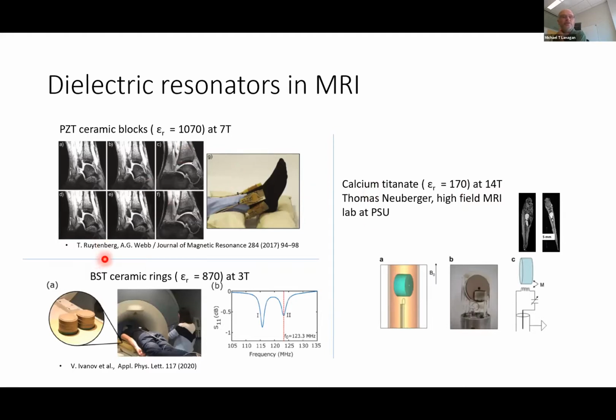Just some examples from literature where we have a dielectric resonator antenna on an ankle shown here, giving a very nice image. This one is one that was done, I believe, in St. Petersburg, where very recently they did some breast imaging using dielectric blocks and then found an enhancement in the signal to noise ratio. And then here, just kind of reiterating what we did on the zebrafish. So these are all dielectric resonators, a little bit different concept than the previous ones I showed you in terms of impedance matching, because here, not only do we control the thickness, but we also control all the other dimensions.